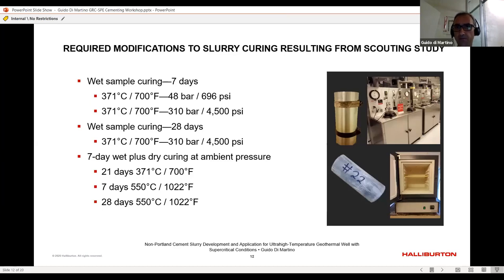In phase two, pre-exposure curing had been revised since phase one. Curing conditions were not ideal, and specimen damage during curing was related to a not fit for purpose procedure. Absence of a permanent contact to water and too short heat ramps were two factors discussed and criticized.